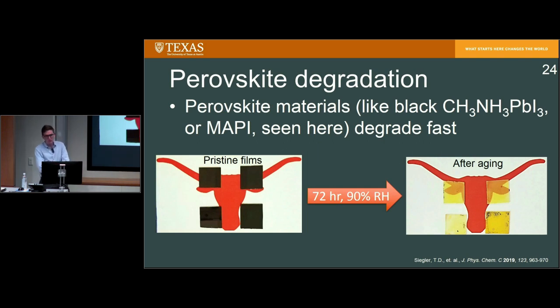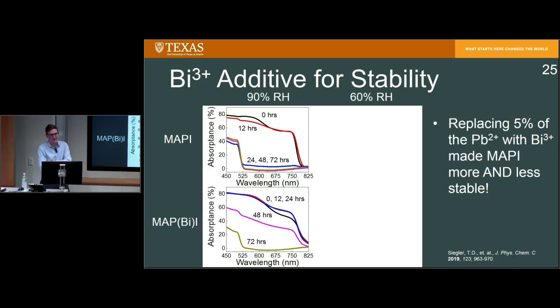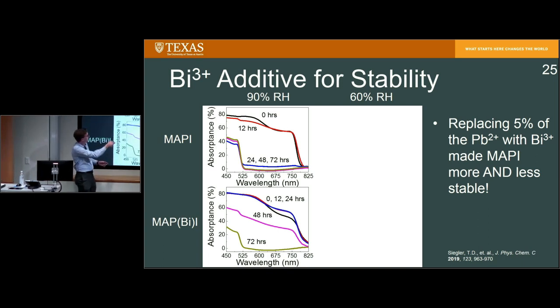And so one thing that I did to try to help stabilize the perovskite is I tried to see if I could do some heterovalent incorporation, some replacement of the lead with a little bit of bismuth, to see if that could stabilize the perovskite thin film. We were able to see that at high relative humidities, we could stabilize the perovskite thin film. The way I know is because of the absorbance, and this is just a simple UV-vis absorbance curve. You can remember it from high school chemistry, maybe you don't, but that's okay. We want this curve to be high in the region between 525 and 750 nanometers, and that tells us you have perovskite, and then when it goes down, the perovskite also goes away. So essentially, don't worry too much about that.